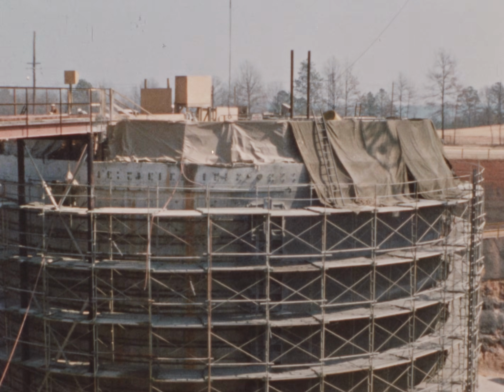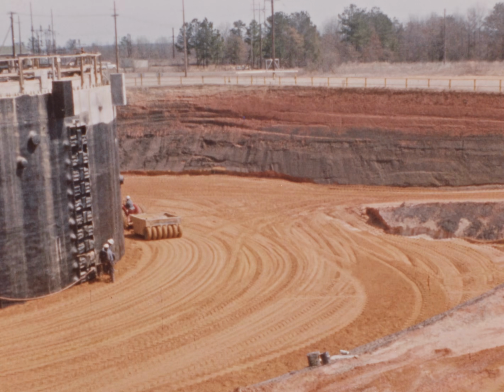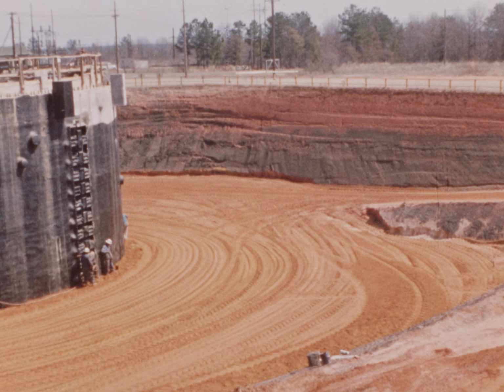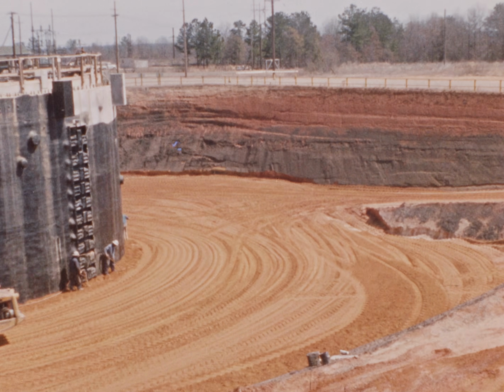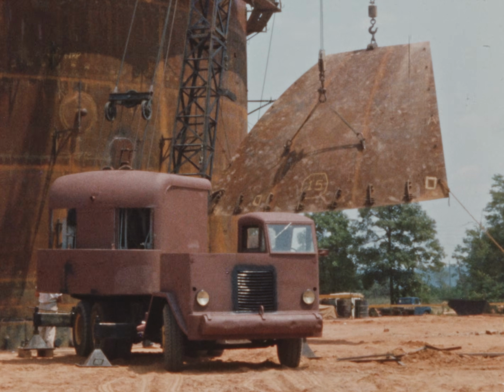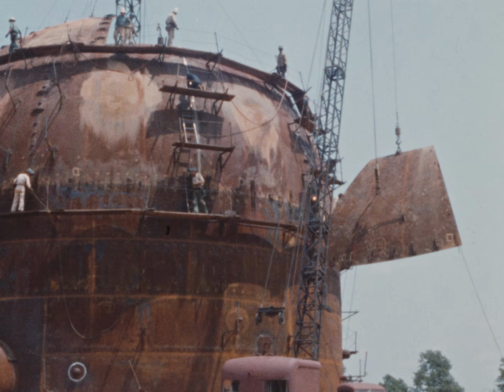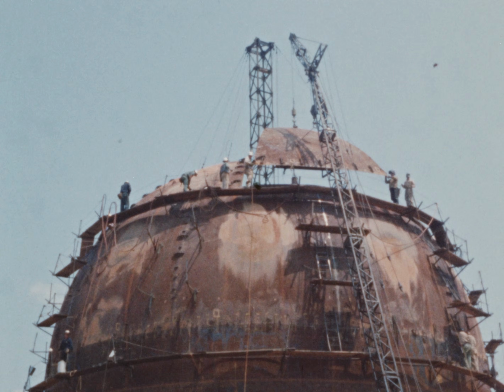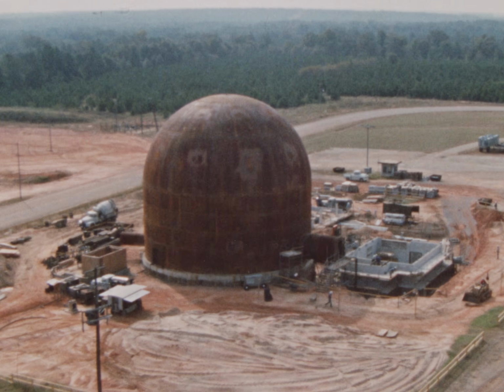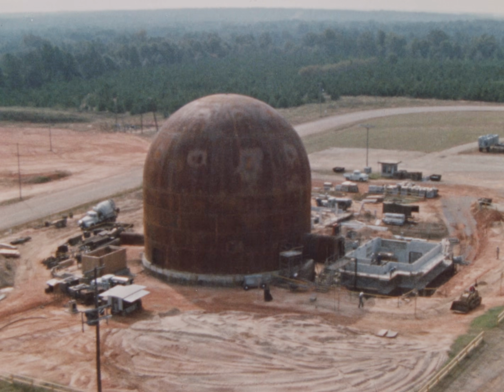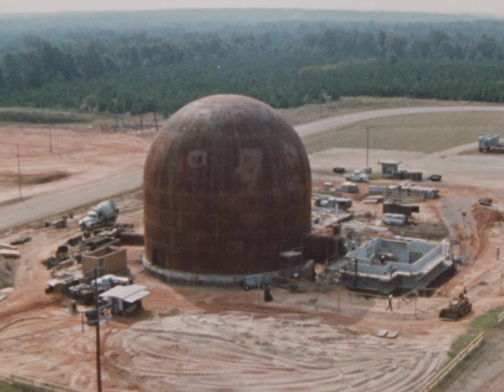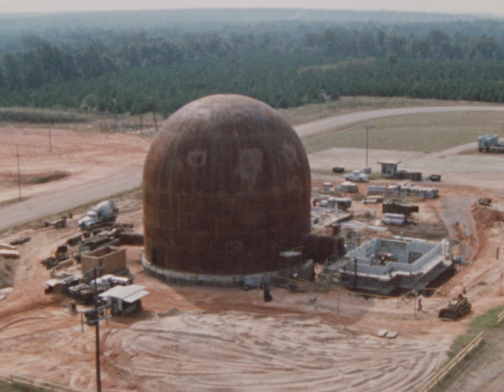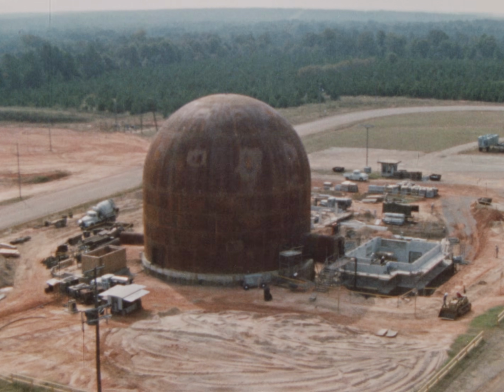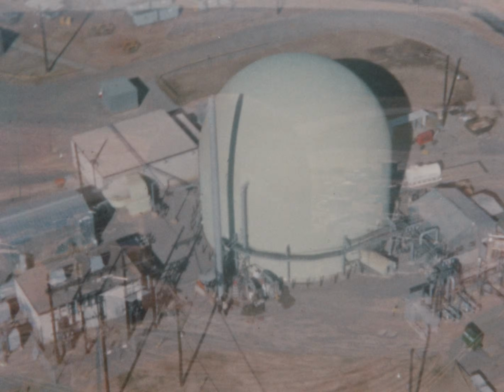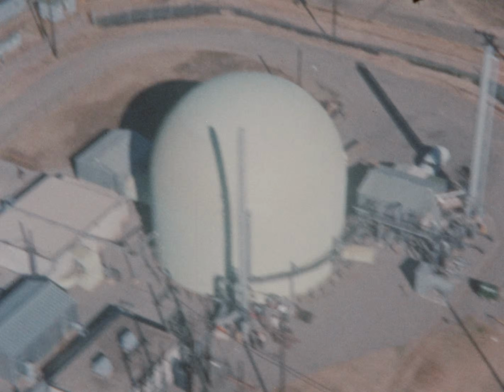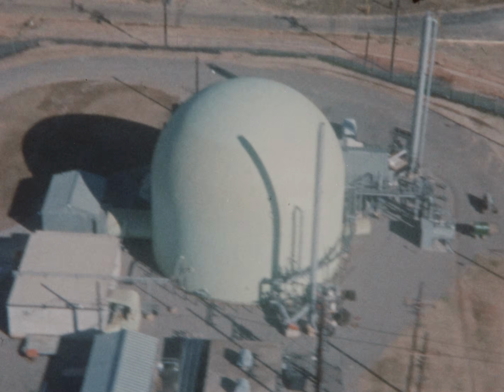After sealing the outside of the concrete wall and backfilling, the 65-foot-high dome portion was bolted to the concrete at grade level. The building was structurally tested at 29 psig and leak tested at its design pressure of 24 psig. A leak rate of only 1% of the volume per 24 hours was specified. Following satisfactory testing, a large section was removed from the steel dome to permit installation of major reactor components.